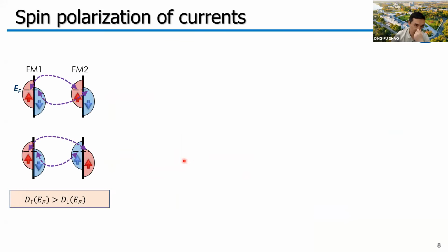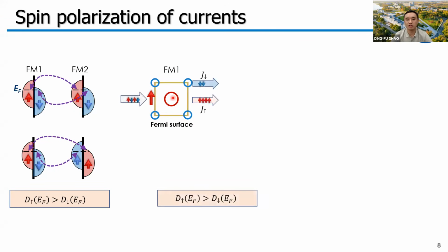We find that this picture may not be accurate because the density of states is the average property of the materials and cannot reflect a specific transport property along a specific direction. Here we want to consider a more accurate picture. So we consider we have a ferromagnetic metal where in its Brillouin zone, we have a spin up Fermi surface here and the spin down Fermi surface here. And because the volumes of the spin up and spin down Fermi surfaces are not the same, if we apply an electric field, we will naturally generate a spin polarized current.